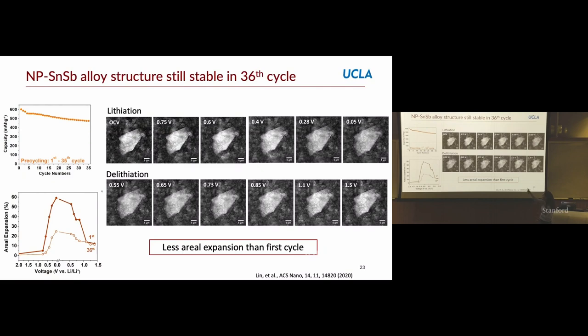So this is the tin antimony again. We still have those nice distinct particles that we saw in the pristine material, and we still have a small volume change or areal change. If you plot the areal expansion, the first one's a different battery, different particles, but the first one is plotted there as a solid line. These open circles are the 36th. So the areal expansion is less, but it is still consistent.